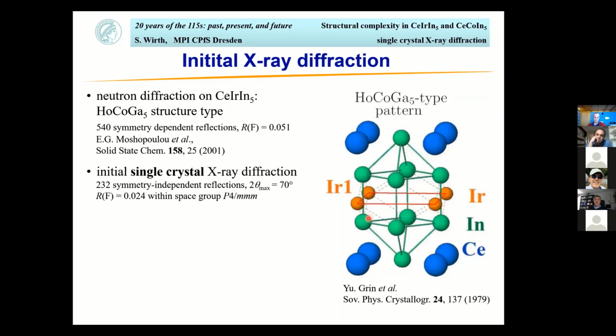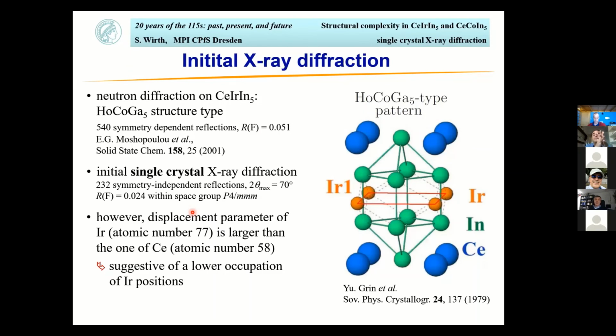Now, typically it's assigned to the holmium cobalt gallium 5 type of pattern, as it's shown here, and it was shown many times during the workshop. So we also did some X-ray diffraction, and you see the results are pretty nice. The R value is 0.024, which is not too bad. But what was noticed is actually that the displacement parameter of the iridium was larger than the one for the cerium. That shouldn't be, because iridium is heavier, so that should be less. So that's suggestive of a lower occupation of the iridium positions.